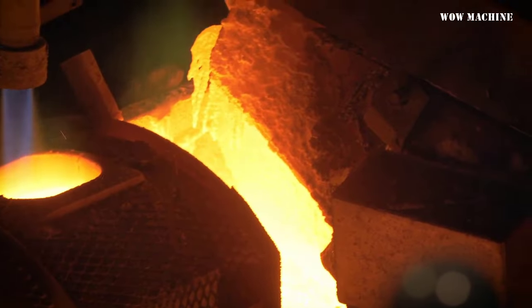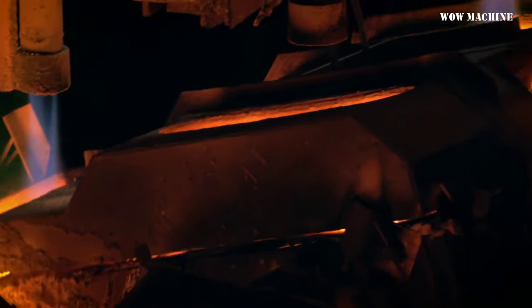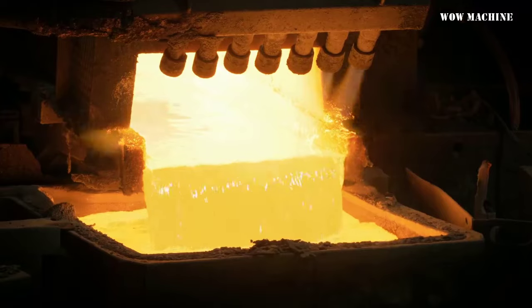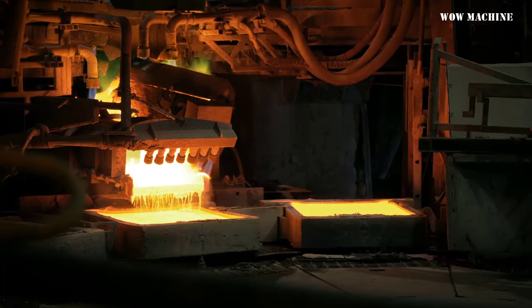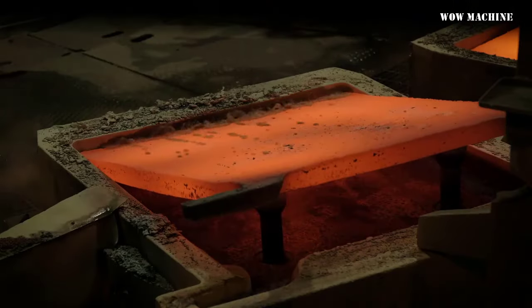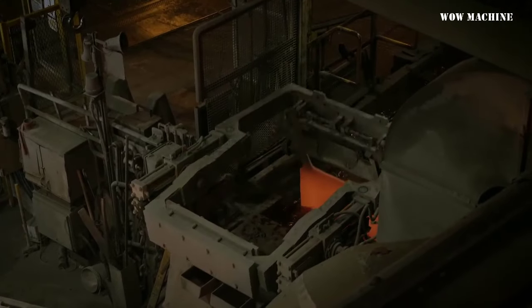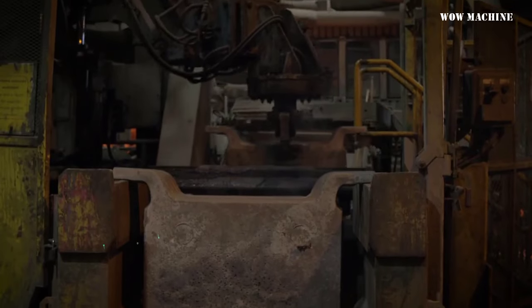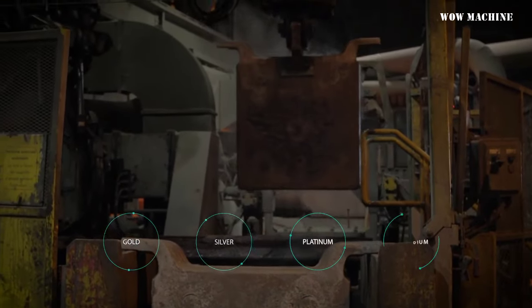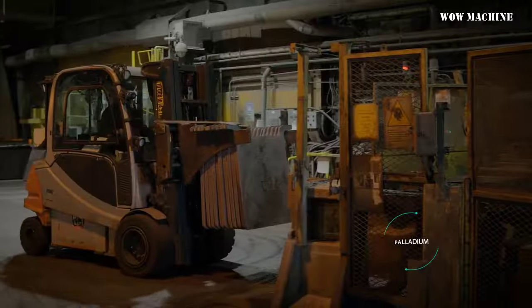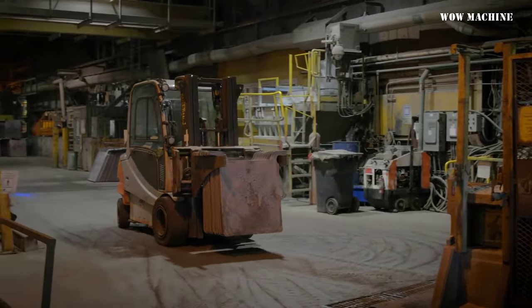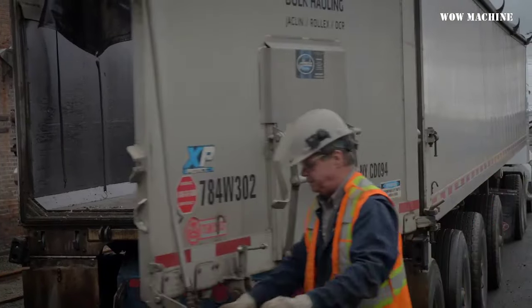The copper, now 99.1% pure, is cast into anodes, which are then cooled with water. These anodes, containing valuable metals like gold, silver, platinum, and palladium, are transported to the CCR refinery in Montreal for final refining.